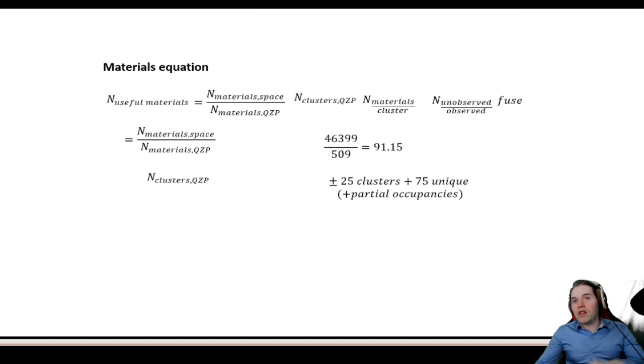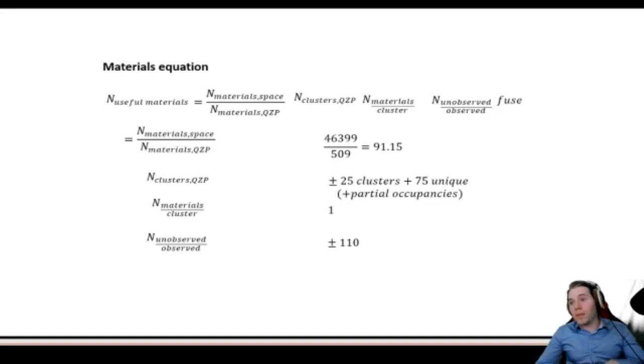Then we need to see how many families there are, and these are also about 100. There are the 25 real families which have multiple crystals, and then 75 which are completely unique. But given how many new crystals we just found in these small families, they're probably just unexplored. So this is again a factor of 100. Finally, the observed materials per cluster are about 1, and the number of unobserved ones, the number of materials we find within each cluster, is again about 100.